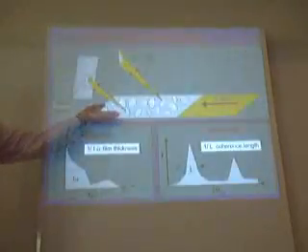It so happens that the natural amino acids don't have enough electrons, so they are not amenable to this kind of analysis. For that reason, we had to elaborate a synthetic program in which we synthesize all these amphiphilic amino acids at the water interface, and we tested again the crystallization and the orientation of the glycine crystals. We found that they are very similar to what we observed in the case of leucine, valine, and these small molecules, and we say that the structure of these clusters must be very similar and therefore relevant to our investigation.